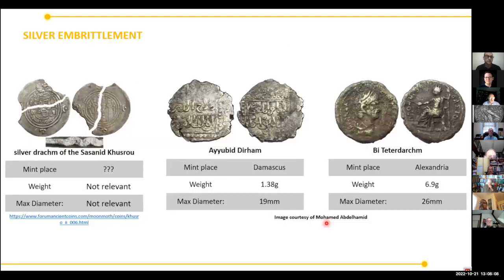Silver embrittlement is actually caused by many factors: burial time and the nature of the environment, salt content, microstructure changes or corrosion, precipitation of impurities that weaken the grain boundaries, and the alloy content with copper and lead, causing intergranular corrosion. If we look here at this example of coins, these coins are actually very brittle and weak, and they might break with improper handling. So we must be very careful when we are dealing with coins like these.